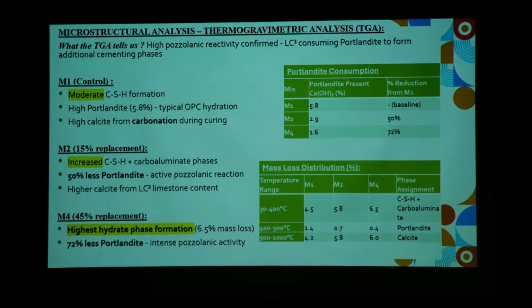So this was verified with our microstructural analysis, the TGA, which showed that at that early stage, our LC3 is consuming the portlandite to form our additional cementing phases. At that early stage, the portlandite is still being consumed, so we're having that temporary increase in pore structure. However, because we're already developing our carboaluminate phases, they are binding our chemical ions and restricting the ingress of chemicals within our concrete mixture itself.